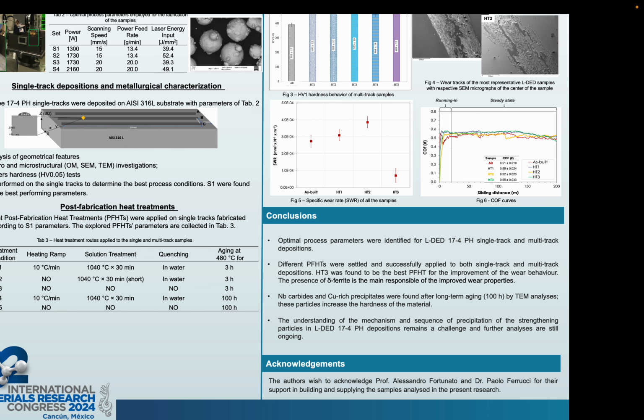As conclusions of this study, it was possible to conclude that optimal process parameters are satisfactorily identified from the 17-4 PH multi-track deposition once the analysis of the single tracks was performed. The different post-fabrication heat treatments were successful for increasing the hardness and the wear behavior of the samples, specifically those samples HT3 with no solubilization, and the sample HT5 with direct long-term aging, in which not only the presence of niobium carbides and copper-rich particles helps to increase the hardness, but also the presence of the delta ferrite helps to increase these properties.